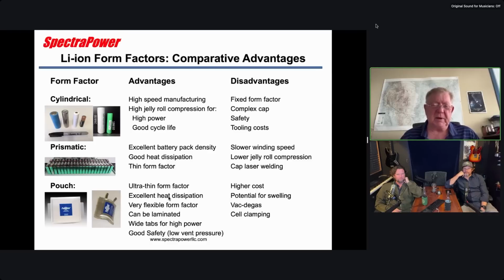They really dissipate heat well because they're very thin. They're very easy to change the form factor. That's why we make them here for people experimenting with different materials for their batteries. You can laminate the electrodes together easily, sort of like you would with a sheet of plywood. You can put a coating on the separator. It's usually like a PVDF or something that will allow you to heat it and compress it and causes the electrodes to be laminated together. You can change the tab size, so if you want to have high power cells, you can put wider tabs in.